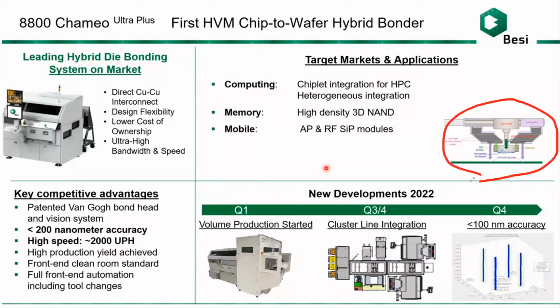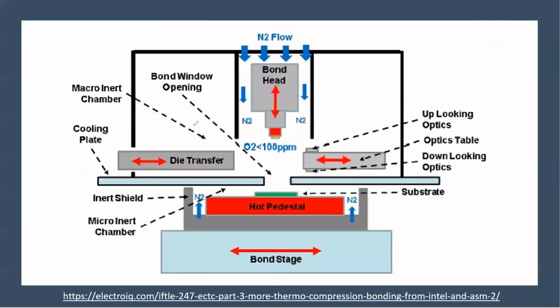And you look at the head here, they call it the patented Van Gogh bond head. All right, so this bond head, they have some tweaks around, but in general, this is not exactly the same. But this is what happens in the bond head area. In the die transfer, the substrate is a wafer, you heat it up and you cool it down at the same time because you want to maintain a constant temperature. And you have tons of optics. You move things around. You need to let the robot know where you're going, so you use the lasers to see where you're going, right? And you bond, right? This is how you bond it with certain pressure, like how many Newtons you want to put it on. And then what kind of environment is that?